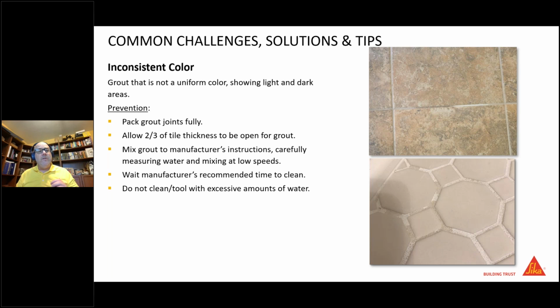Another thing in here for prevention is allow 2/3 of the tile thickness to be open for grout, meaning that I don't want a bunch of thin set or mortar or other stuff inside my grout joint before I go grout. We as manufacturers try to make our grouts dry evenly, at a consistent rate. But when we've got a grout joint that's got highs, lows, highs, lows, what's going to end up happening is the high spot, that area of the grout, is going to dry faster, and the low spot's going to dry a little slower. That could cause shading in that grout joint. I've had instances where I've asked the contractor, hey, hand me the trowel that you used to install this tile. I set it right next to the grout joint and I can actually see light, dark, light, dark that matches the tooth of the trowel, because that grout joint wasn't cleaned out well enough.